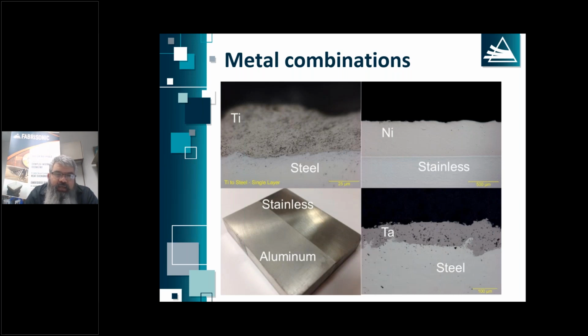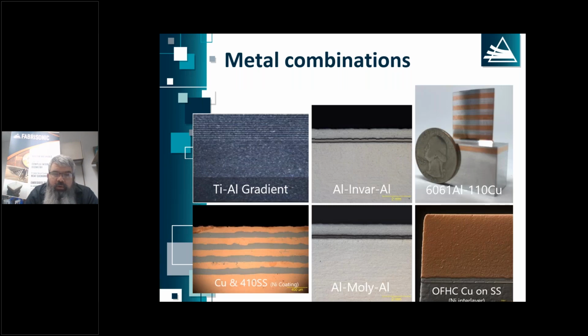A lot of these applications right here I would consider cladding. Certainly we're building them up layer by layer, so it meets the definition of 3D printing, but the end goal is to clad material A onto cheap material B typically. Looking at more along the lines of custom materials, we see some gradients here. The titanium aluminum gradient is heavier in aluminum on the top and heavier in titanium on the bottom. And this was actually designed as an armor product. So we're engineering a material with a variation in the material properties through thickness.